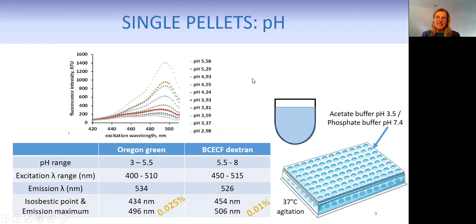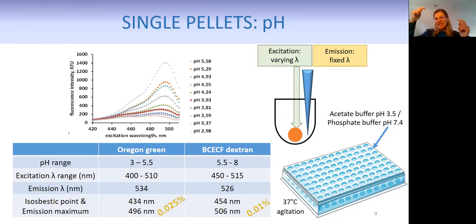So we performed this dissolution test combined with the pH determination from single pellets to observe the drug release from one pellet in correlation with its very same pH. The pellet was immersed in the dissolution medium, either acetate buffer 3.5 or phosphate buffer 7.4. At predetermined time points, we sampled the dissolution medium and analyzed it with spectrophotometry for the quantitative analysis of drug release from the very pellet. In the meantime, we did the fluorescence test, measured the emission of the fluorescence intensity, and were able to correlate the pH which is created in the pellet. We also had a very transparent film coating, so we could actually measure through the coating and see what's happening within the pellet in terms of pH.